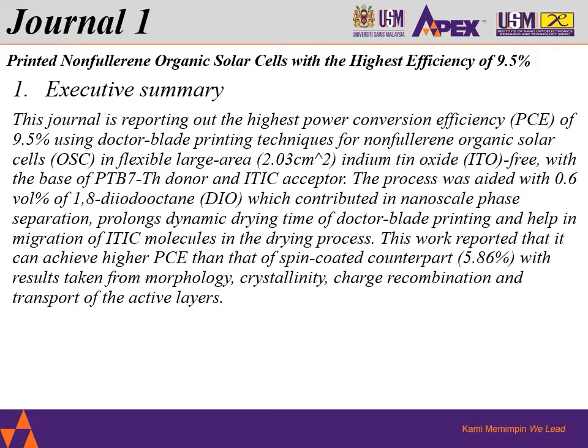The process was aided with a 0.6% volume percentage of 1,8-DIO, and this is a solvent additive, which contributes to nanoscale phase separation, prolongs the dynamic drying of Dr. Blade printing, and helps in the migration of ITIC molecules in the drying process. This work reported that it can achieve higher PCE than that of the currently spin-coated counterpart, or the current technology, of 5.86%, and the results were taken from morphology analysis, crystallinity, charge recombination, and transport of the active layers.